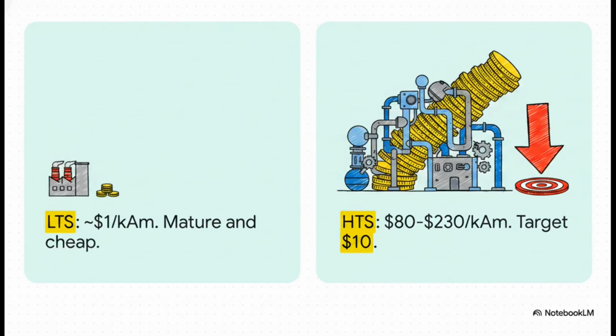Mature, easy-to-manufacture LTS costs about $1 per kiloamp meter. HTS, on the other hand, currently sits anywhere between $80 to $230. That's purely because of that highly complex, low-yield vacuum deposition process we looked at earlier. To even be competitive for widespread power sector use, the HTS industry has set a massive target for 2030, dropping that price all the way down to roughly $10.